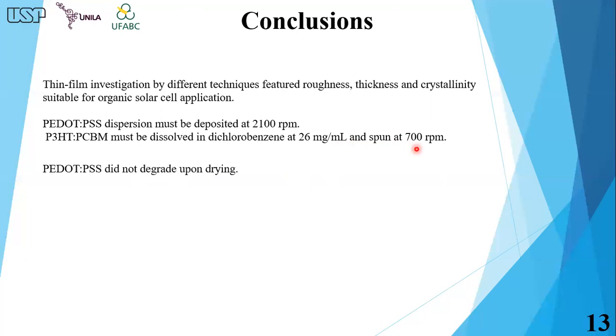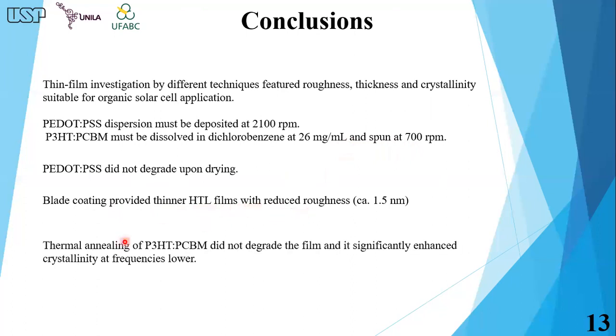PEDOT:PSS did not degrade upon drying. Blade coating provides thinner films with reduced roughness. The thermal annealing of P3HT:PCBM did not degrade the films and it significantly enhanced crystallinity at frequencies lower.